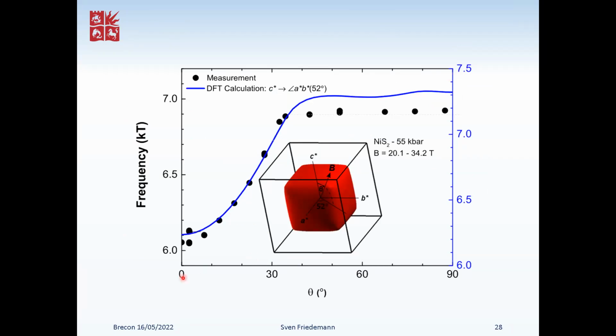So this is a rotation study where we observe how the frequency increases as we rotate the whole pressure cell, including the sample. All of this is done at very high magnetic fields, and it fits quite nicely with the DFT calculations overlaid as the solid line. So we've got a good understanding of the Fermi surface, and in particular that it looks like the DFT U equals 0 Fermi surface.